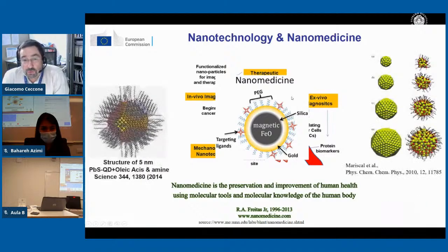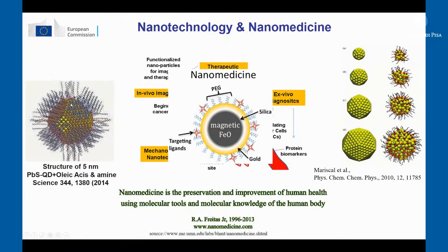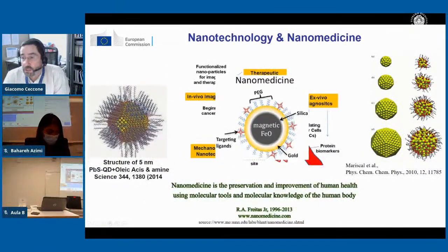But in fact, what you normally get is something more like this, in which the nanoparticles are definitely not spherical. They have different kinds of faceting, and the functionalization is not uniform, like you can see in the cartoon, but is definitely denser on one facet and less dense at the cusps. And also, when you go to the right side, you can see that by increasing, for instance, just the gold, you increase the faceting, and you have the thiols, which are bonding to the gold in a different way, depending on the dimension and on the structure of the particles.